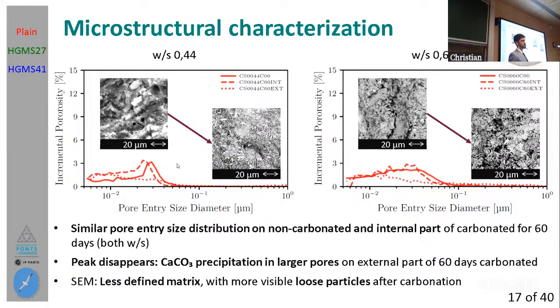Then if we take a look at the results on the external part, you will see a complete disappearance of this peak, which could be related to some precipitation of calcium carbonates. And also what you can see is that that doesn't change with the different water to solid ratios on the left and on the right. And also, what can be more noticeable in these two cement images here is that before carbonation, we have a more defined cement matrix. And here we have a less defined cement matrix and some calcium carbonate crystal precipitation, which is noticeable.